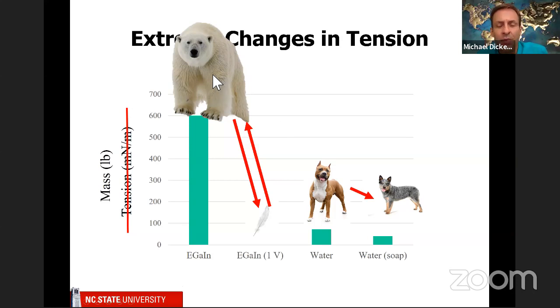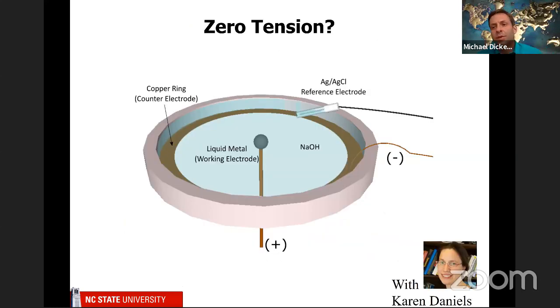In our case, we've got something that's like a polar bear. It's absolutely huge. Polar bears are about 600 or 700 pounds. But when we apply 1 volt, we make it light as a feather. In fact, even lighter, maybe like nothing, maybe like air. So this is kind of crazy. I keep telling you maybe the tension is zero, and we've been working with Karen Daniels to understand this a little better. In this experiment, we take a droplet in a petri dish, apply a voltage to it, and look from the top down. And right where that data looked like it was going to hit zero, let me show you what happens.